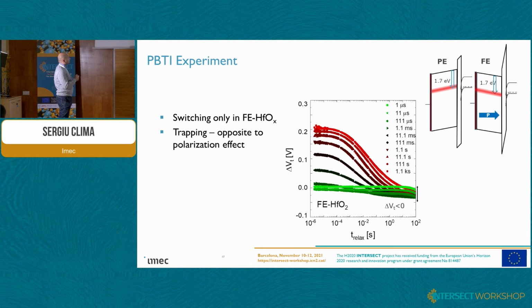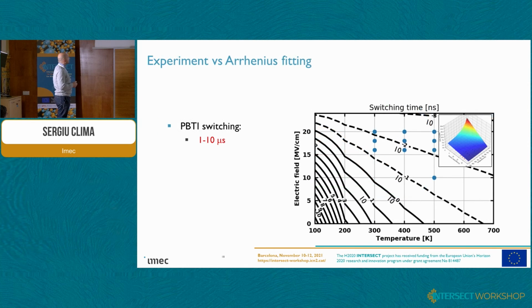Johannes already discussed a lot about the trade-off between charge trapping and polarization, and they counteract each other. But we could say that our measurements were quite lousy in the sense that the experiments were slow, and we measured in the range of microseconds.